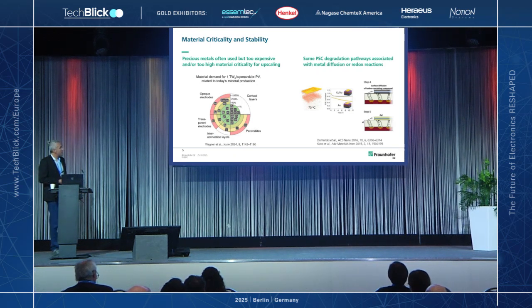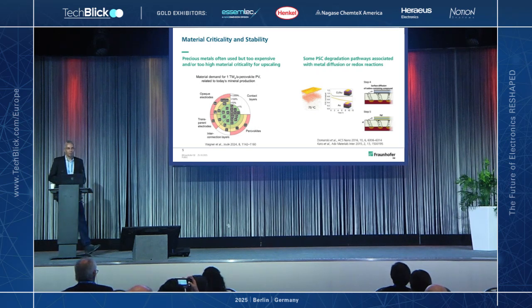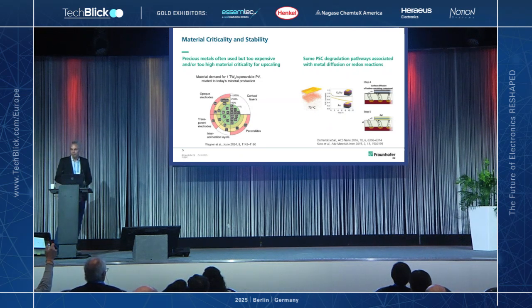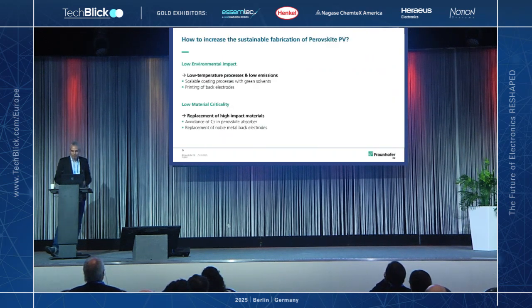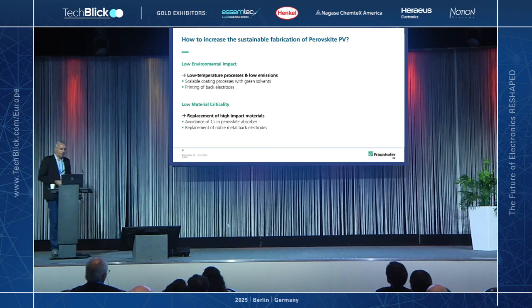And at the same time, some of the metal back electrodes, which are typically applied in the layer stacks, are associated with degradation mechanisms. So, for example, you can find gold migration throughout the layer stack, leading to detrimental device performance over time. And also some degradation mechanisms are related to the presence of silver and silver iodide being formed when you have this as a counter electrode. And this was our starting point, a bit where we thought how we increase the sustainable fabrication of perovskite PV.